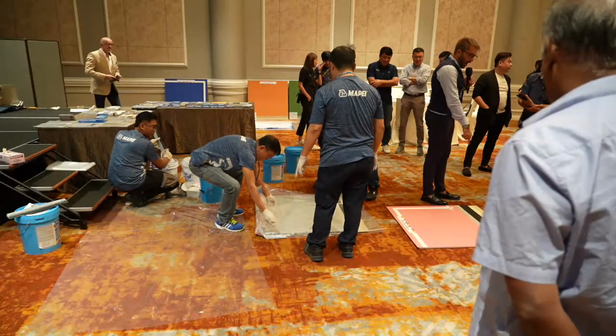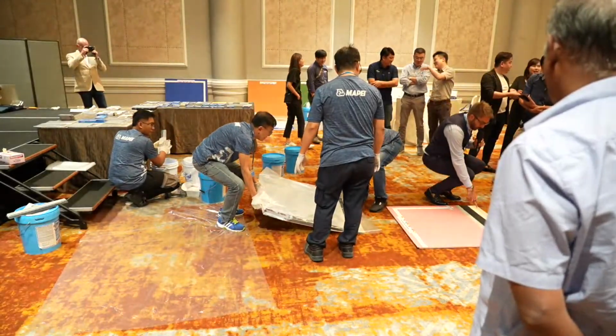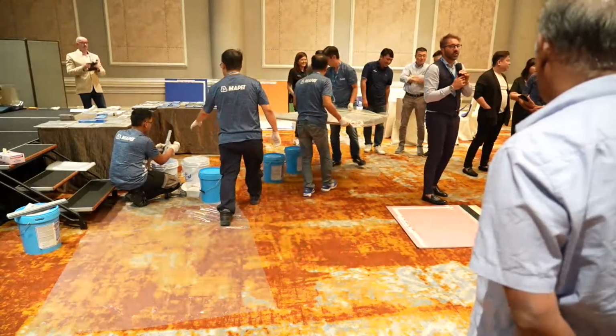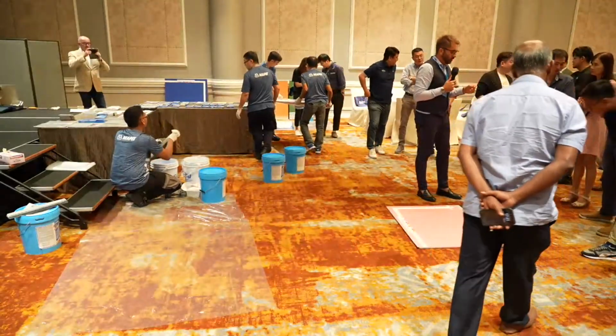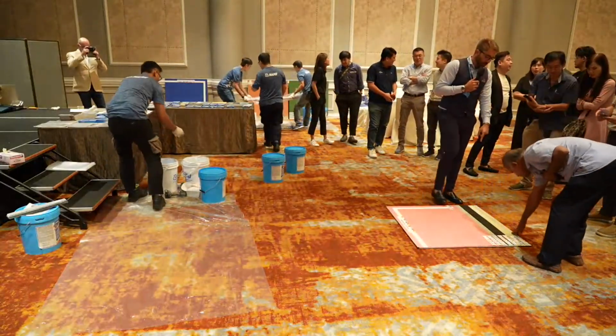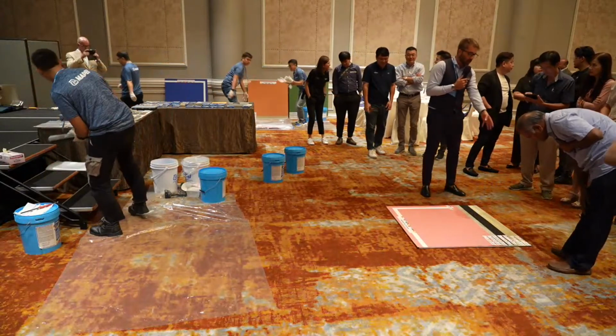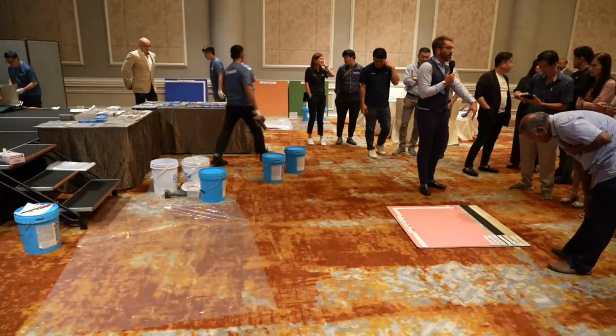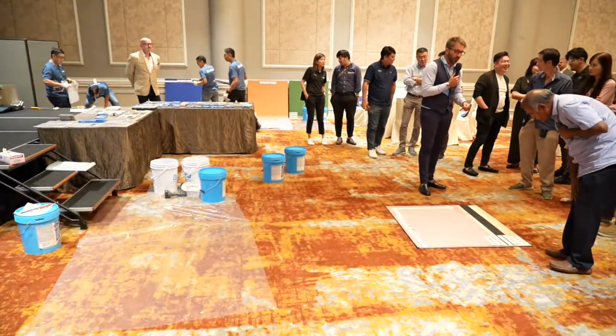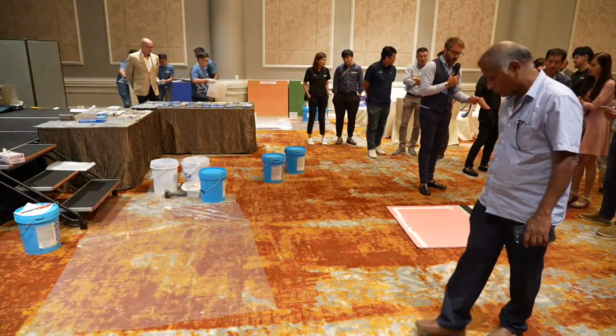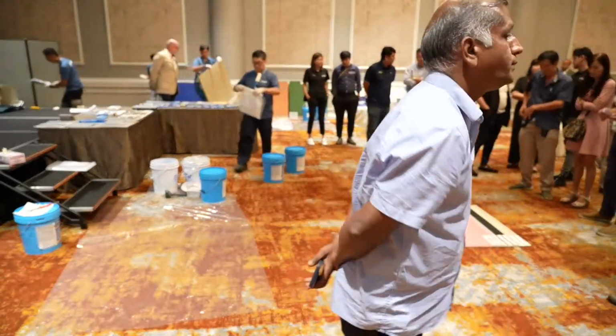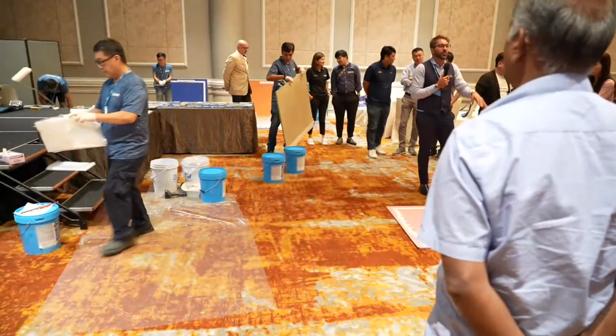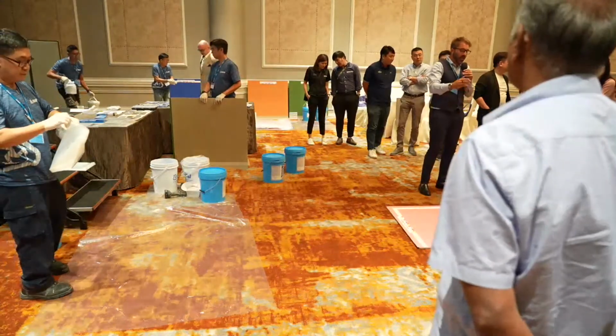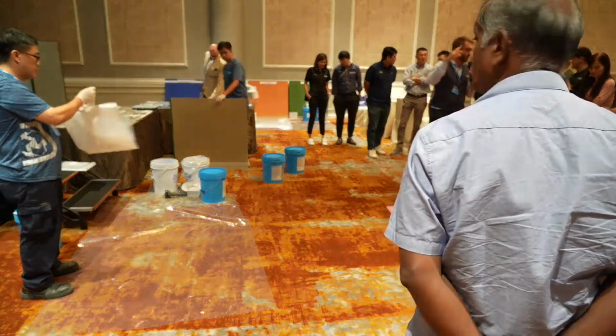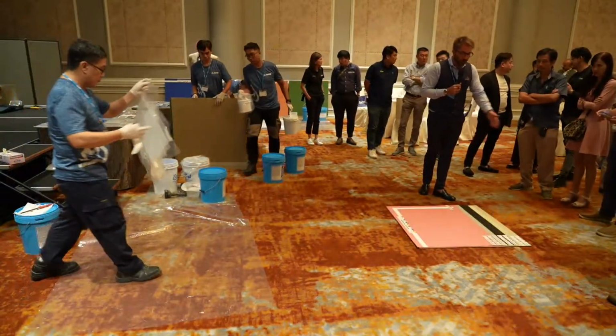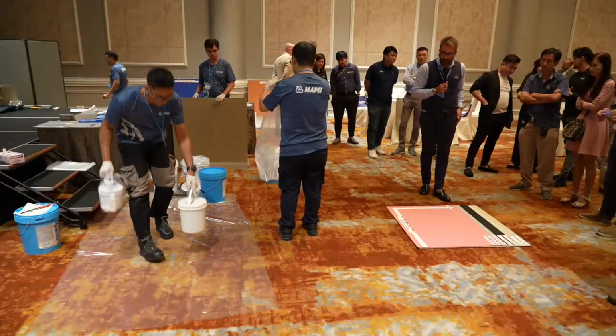An important thing to know is why we use the primer between the rubber mat and the acrylic resin. Not only for the adhesion. The adhesion is good also if we apply the coating directly on the rubber. But with the primer, we want to avoid any kind of migration of the plasticizers contained in the SBR, so the primer avoids any kind of migration of plasticizers. So we improve the durability. We are improving the adhesion thanks to the epoxy primer.